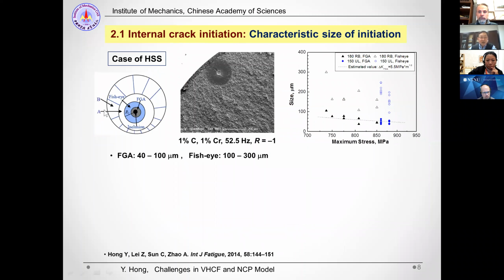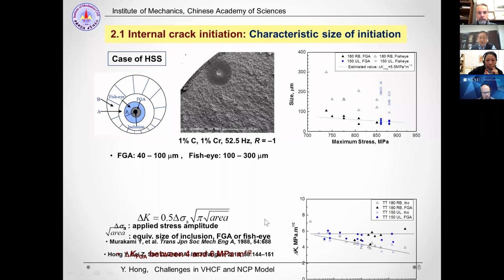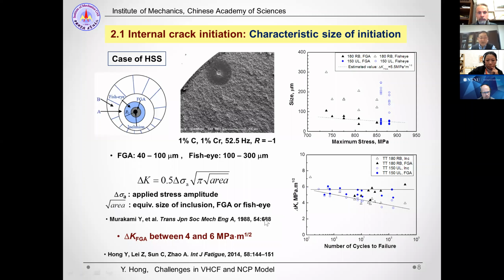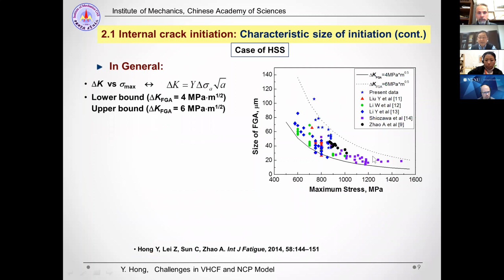And then we try to measure the size of FGA, this crack initiation region, and the value is between 40 and 100 microns, like the data showing here. And also, we try to calculate the delta K value for this region in relation with the strength and the size of the defects. And the value for the delta K FGA is between 4 and 6 megapascal root meter, like the data showing here. And also, we collect a large number of data from the literature, and then we put two boundaries. One is the upper bound of 6 megapascal root meter, and a lower bound of 4 megapascal root meter. And we can see almost all the data points within these two bounds.